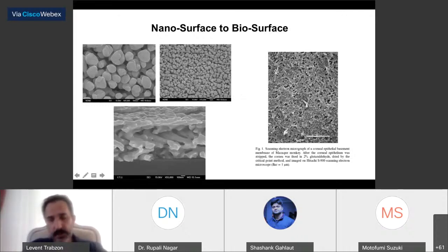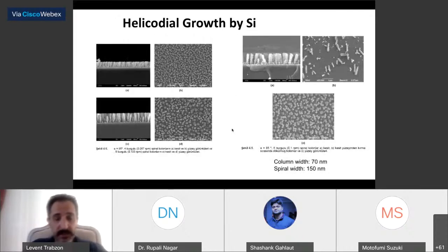So we realize that we can grow nano-dimensional surfaces by GLAD, similar to the membrane structure, on which you can grow epithelial cells, and we have done it. We have grown such films based on silicon. As we have already discussed in detail in the previous talks, you can easily make helicoidal growth with silicon by changing the turning speed, the RPM value of the substrate, or by changing the deposition rate.